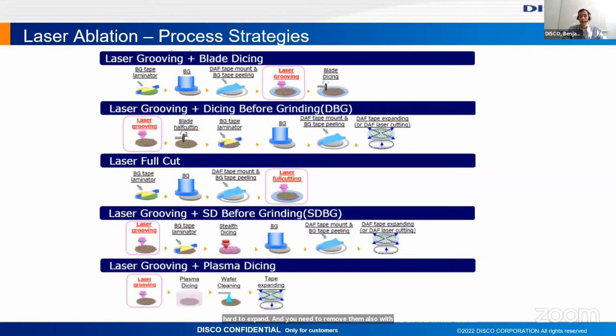And last but not least, we teamed up with an American company called Plasma-Therm, who is providing plasma dicing equipment. So shout outs to my colleagues from Florida. Here the idea is that with the laser, we can remove, again, metals that cannot be plasma diced, or also open the resist. You can also use our spin coating as a resist for the plasma dicing, and then the laser grooving opens the resist at the positions where you want to interact with your plasma.